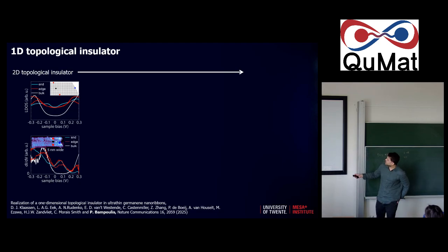Same thing in the theory. You see that the end of the nanoribbon and the edge of the nanoribbon are about the same. There's a little bit of a difference in the actual shape from what you would expect from a topological state, which is a 1D state, so it should be constant, filling the gap. In the experiment, however, because you have something going from K to K prime point, it's a zigzag edge, and tunneling in STM is predominantly happening from the gamma point. You have this K parallel contribution, which leads to a kind of Gaussian shape of your density of states. So instead of having a constant shape, you have something that is decaying with voltage. That's why we have this discrepancy between the two. But we can understand this well, and we can also fit it, and it fits well.